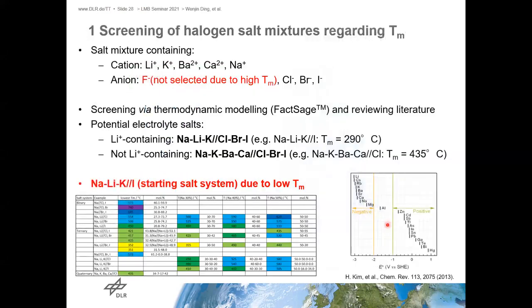Regarding the potential, the salt mixture should contain only cations like lithium and barium ions, because they should be more negative than the sodium metal, to have chemical compatibility with the sodium metal. And we also use the FactSage simulation, the thermodynamic modeling, to review this, and also review the literature.